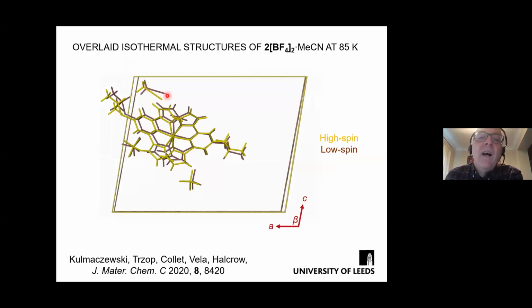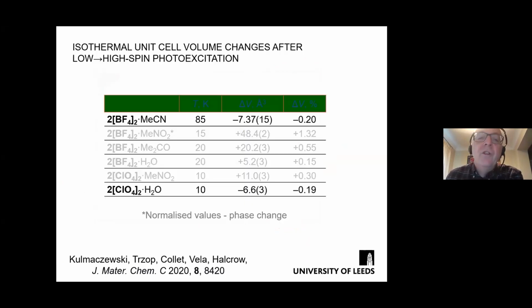because the low spin state has a much more canted monoclinic unit cell angle than the high spin state does. And this canted unit cell angle, even though the A, B, and C dimensions are a little larger, reduces the volume of the unit cell a little bit to give us this unusual effect. And in fact, 2 of these 6 solvates that we measured by photocrystallography have this unusual, small but real negative unit cell volume change during relaxation.